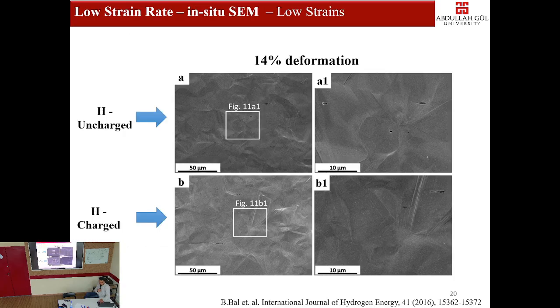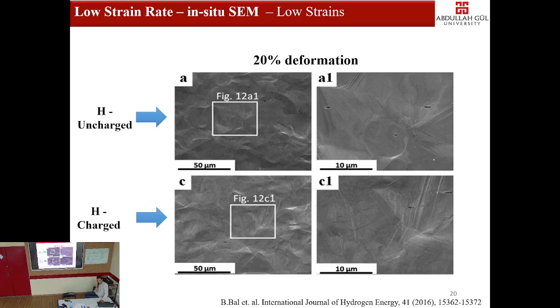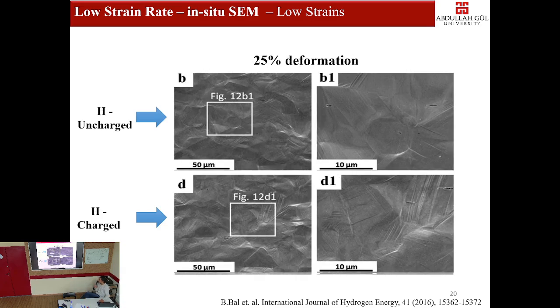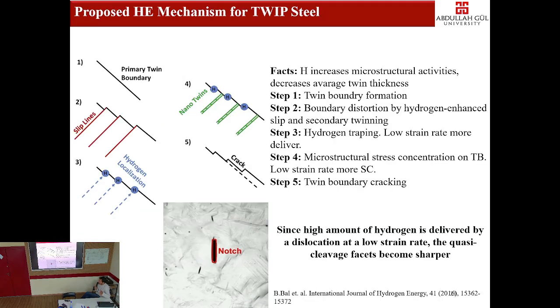Again, we measured the dislocation density. With 14% deformation, we see some marks with hydrogen where we don't see anything without it. So hydrogen maybe increased localized plasticity. Again, at 20%, hydrogen increased the microstructural features: more defects, more slip lines with hydrogen. At 25% deformation, same. So for TWIP steel, we didn't have any hydrogen embrittlement mechanism, but we proposed one.